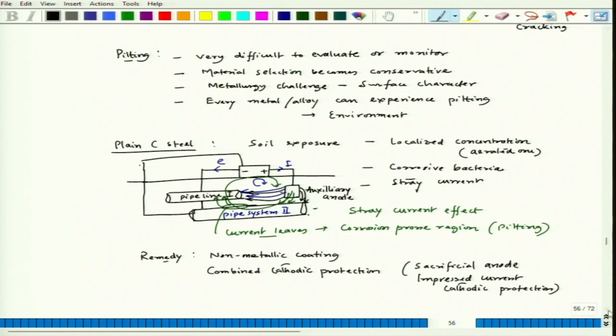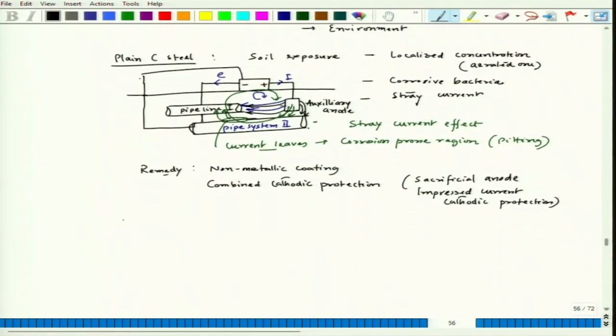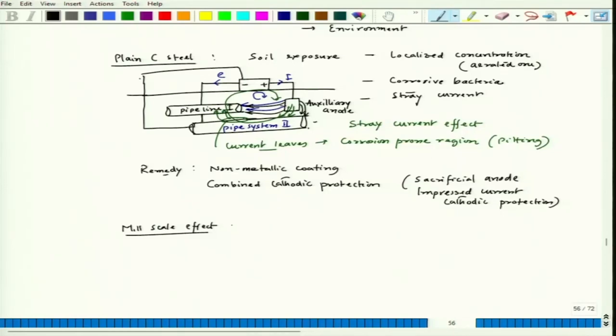So, these two methods can be useful. Similarly, if we try to see the mill scale effect. In plain carbon steel, if it is hot rolled steel, then there would be a thin layer of oxide that remains on the steel. That is basically nothing but the mill scale, and if that mill scale remains on plain carbon steel and there is a break in that mill scale. So, let us say this is my steel surface and we have a mill scale. Let us say this is my cross section and this is the mill scale.